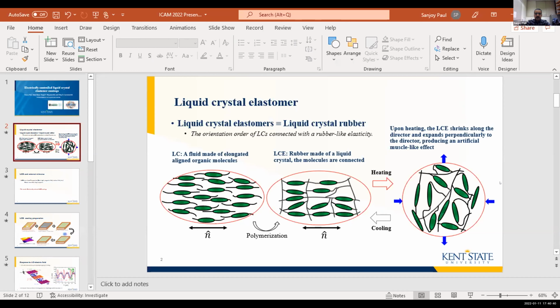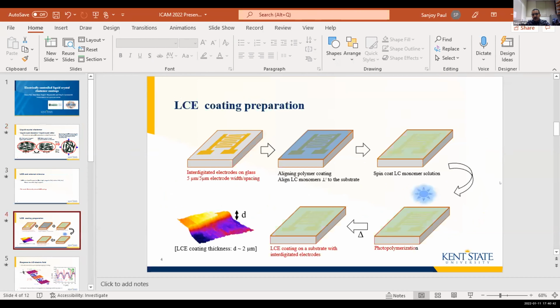As I mentioned, in the coating process, we coat a polymer like a polyimide that helps to align the liquid crystal molecules perpendicular to the substrate.